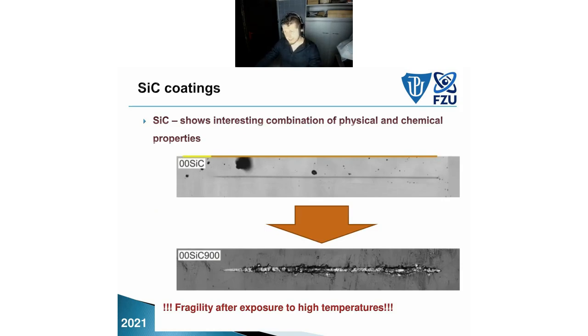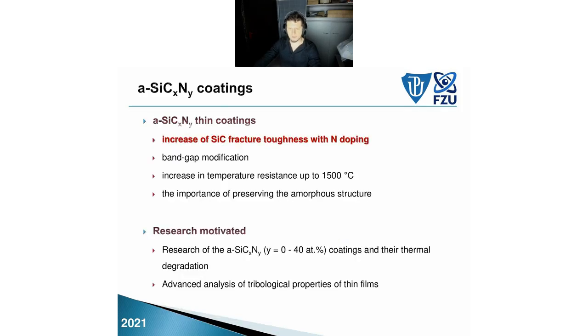But silicon carbide actually has the same issue as titanium nitride and titanium aluminum nitride. It has a problem at higher temperatures. These are pictures from our own research. You can see scratches on silicon carbide, and on the same silicon carbide after annealing at 900 degrees Celsius. After exposure to high temperature, you can apparently see some increased cracking, increased brittleness.